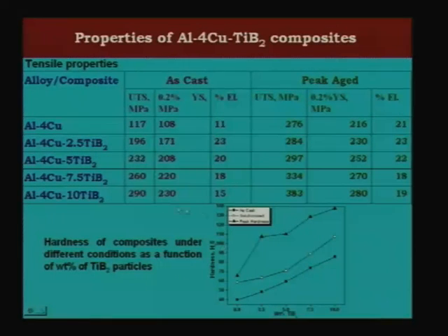But the thing is, if you carefully observe, the increase is much higher at smaller volume fraction. If you go to higher volume fraction, it is decreasing, and if you go to probably 20% volume fraction, then it further decreases, because whatever may be the compatibility, TiB2 is anyway a brittle intermetallic compound. It is a hard compound. So if you keep on increasing the volume fraction of the hard phase, you cannot expect the elongation to keep on increasing. If you carefully observe, the elongation keeps on decreasing here. At small volume fraction you have a much higher elongation, but as you keep on increasing the volume fraction, the elongation decreases, and 10% gives you only about 15%.